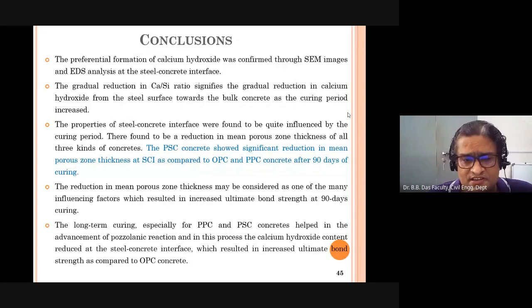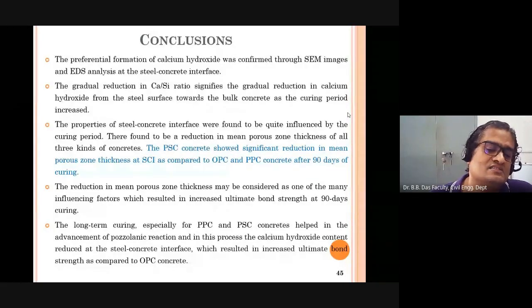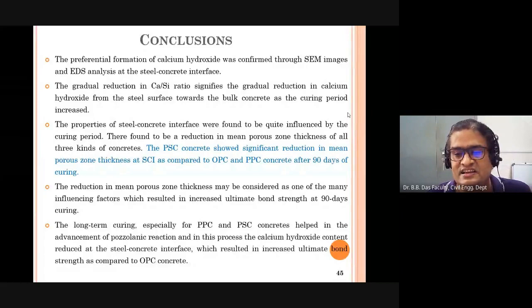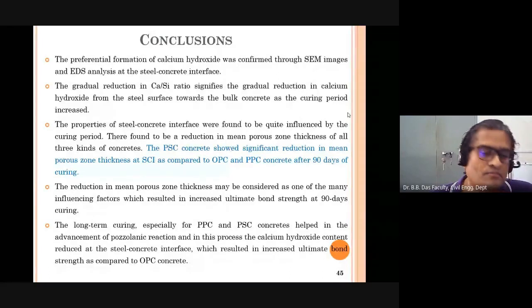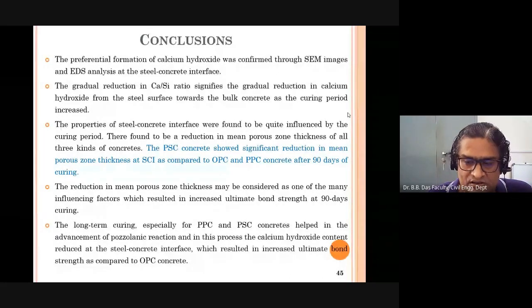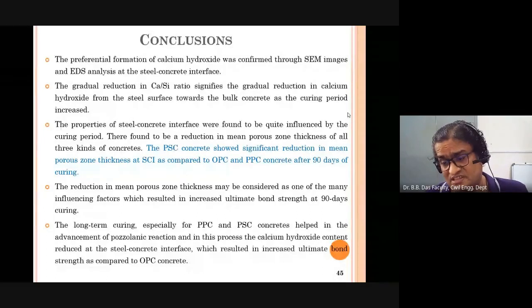The long-term curing, especially for PPC and PSC concrete, helps in the advancement of the pozzolanic reaction, and in this process the calcium hydroxide content is reduced at the steel concrete interface, which resulted in increased ultimate bond strength as compared to OPC concrete. We know it very well. With the long-term curing for PPC and PSC, both cements having a secondary cementitious material, it is helping in the advancement of the pozzolanic reaction. That is key.